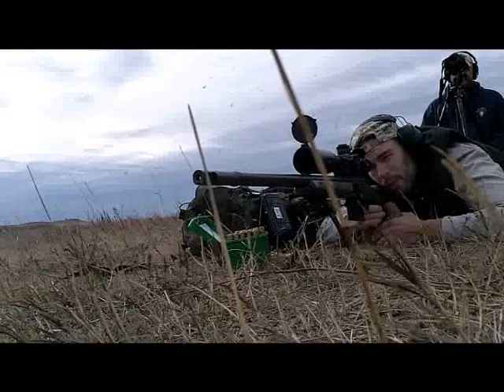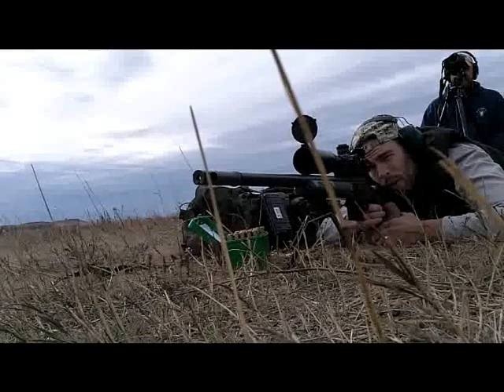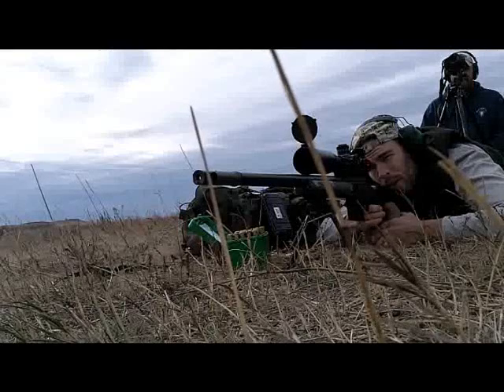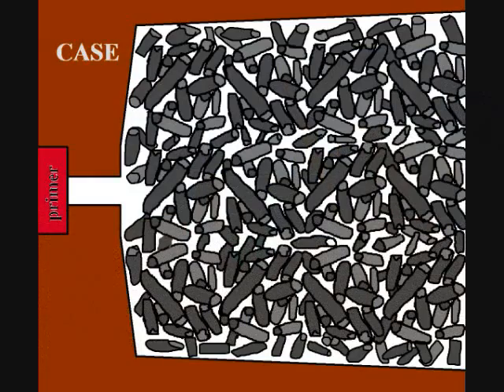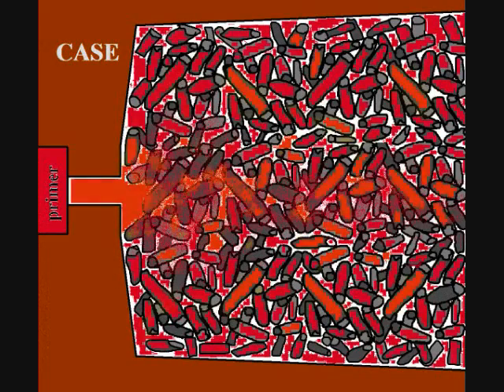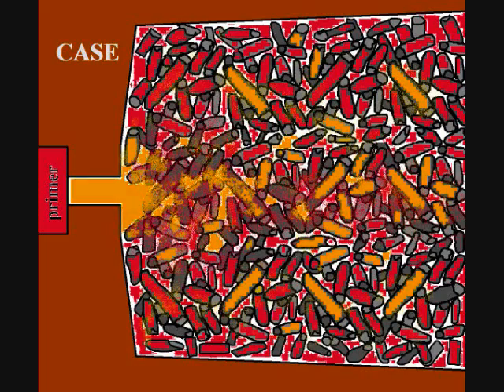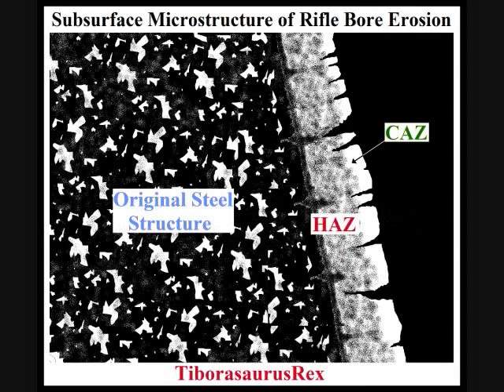So you have this almost instantaneous increase in temperature from normal room temperature, especially on a cold bore, to 3,700 degrees instantly. And the source of this heat is obviously mostly from the gas propellants, and also there's frictional heat. You got the bullet sliding through that steel rifling, and that's going to significantly increase your heat as well. So the result of this is you're going to have a temperature affected zone. And this is going to be a couple hundred microns deep in some cases. And obviously this varies on what kind of steel you're using, and what kind of cartridge you're shooting is going to have a huge effect on this.